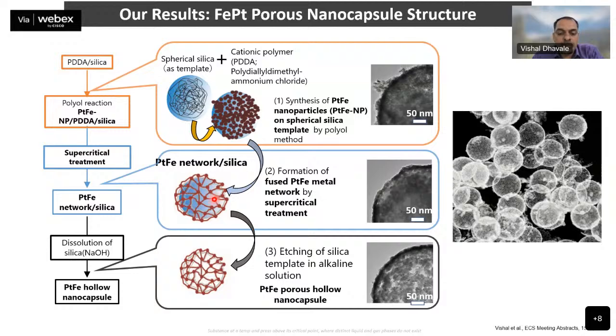In this supercritical treatment, the actual distinct liquid and gas phases do not exist. So we'll have very good connectivity between the two particles, and a network gets formed, which gives internal strength to the network. Eventually, if you leach out the silica which is inside, you can see the transformation from this to this. So overall, a hollow nanocapsule can be formed, and you can see the dark field imaging here. You can see the porous network structure of the FePt.